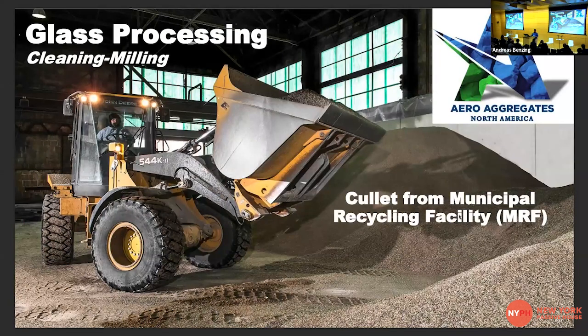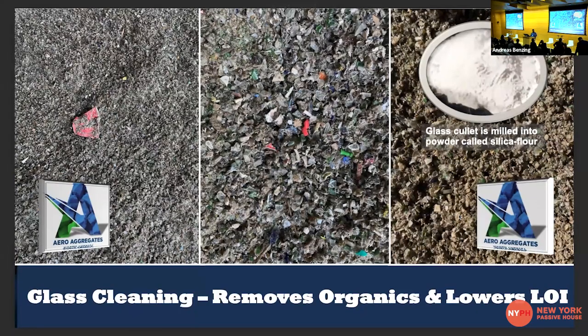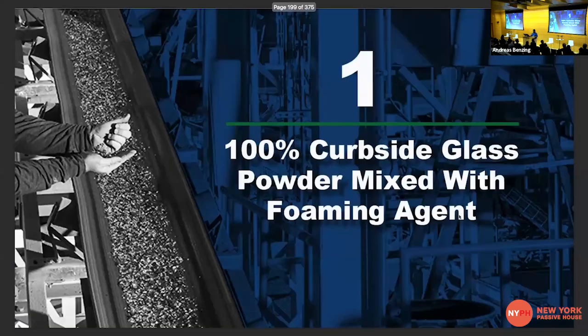So the same as, again, Mr. Grasso, we have to clean the glass. We take the glass from the municipal recycling facility, the small particles of glass, and then we have to clean it, and then we have to mill it. It's very dirty. There's a lot of organics in it. What we're trying to do is remove the organics from the glass so we get it right back down to a pure mineral. So we look at the LOI, the loss on ignition, we test it, and we get the loss on ignition to a very low point, so we have a very low amount of organic material on board. It's 100% curbside recycled glass.